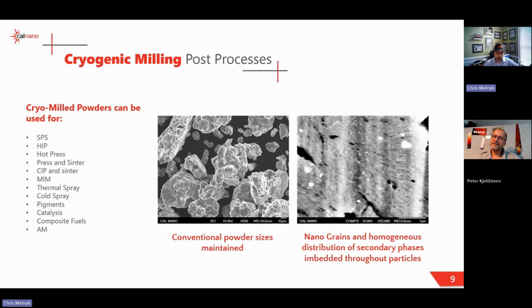So we can go even further than that because, the classic example is you can only add so much sugar to your water before eventually it stops dissolving and it just settles at the bottom. Sure, you can heat up the water, get a little bit more in there, but eventually that's it. But if you start off with snow and ice and you're working in a freezer, you can mix any ratio you want and blend them, and you could have 80% sugar if you want with uniformly distributed water in the form of ice. So we're not limited. We can add whatever ratios of whatever materials, and we're never going to melt them.